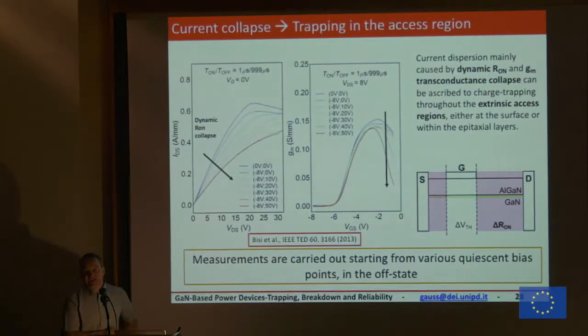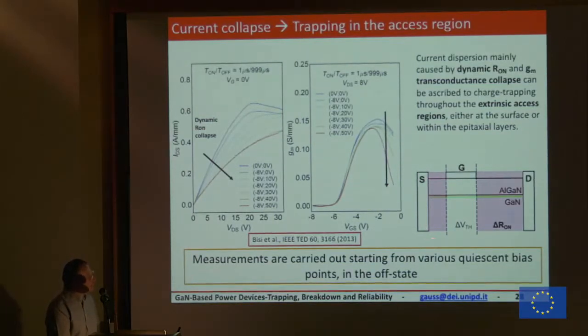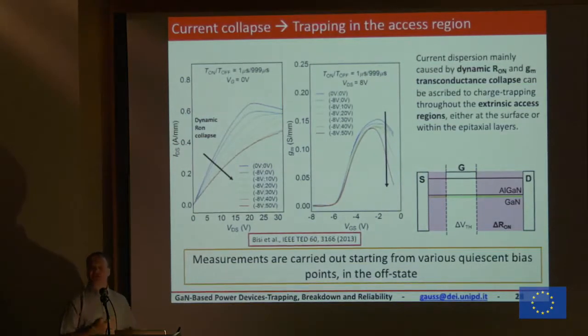In this kind of device, instead, we have again a current collapse, but looking at the GM versus VGS, or let's say ID versus VGS, we see that there is no threshold voltage shift at all. So we should not have any traps charged under the gate. But since we have a drop in the maximum of the transconductance at large VGS, we are having trapping in the access region. So we can try to localize traps now. But unfortunately, we cannot say in which layer they are, at the surface or in the buffer. But with some experiments, changing the passivation, doing some really good test structure design, we may understand this. But of course, this takes time.